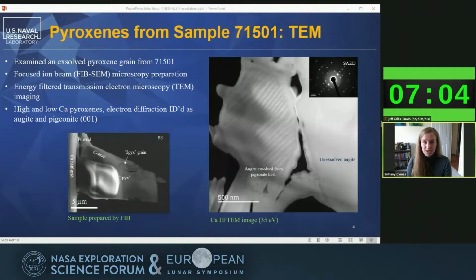So we looked at one of these very interesting grains. We prepared a pyroxene from sample 71501 for analysis in the TEM using our FIB-SEM. You can see our final sample here in the secondary electron image. This pyroxene sample actually has two pyroxenes. The main target here is labeled 1 pix, and adhered to the surface is our exsolved grain labeled 2 pix.